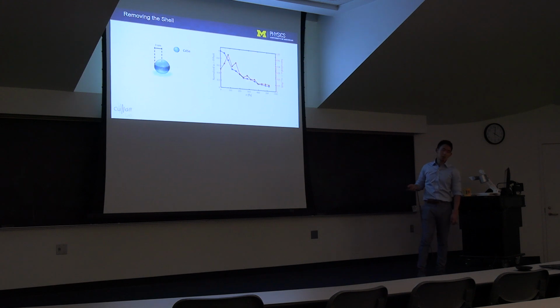And we can try one other thing, which is to see the effect of modifying our material somehow. Specifically, we repeated our experiment on a different sample consisting of only a cadmium selenide core. And what we found is that the long rise of the sideband disappears, and the dephasing dynamics become exponential. And because the exciton confinement radius doesn't significantly change between the two samples, the main difference of this bare core sample is that the nanocrystal surface is now closer to the excitons. So this made us wonder whether the nanocrystal surface matters in the dephasing dynamics on these short timescales of these nanocrystals.